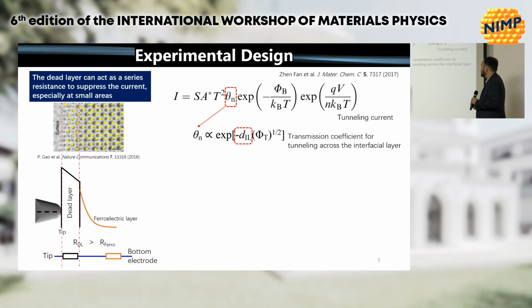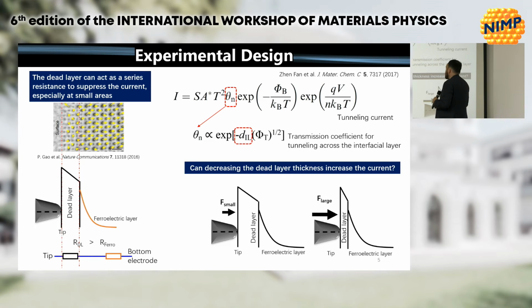the injected current. If we look at this representation of tunneling current, there's a term, the transmission coefficient, for tunneling across the interfacial layer. And if we look at this and you think about thinning that interface layer, then in principle you could enhance the current. So that's the proposal here. Can we decrease the dead layer thickness, and can that cause an increase in current, where the current is largely coming from some tunneling current through some injected charge?